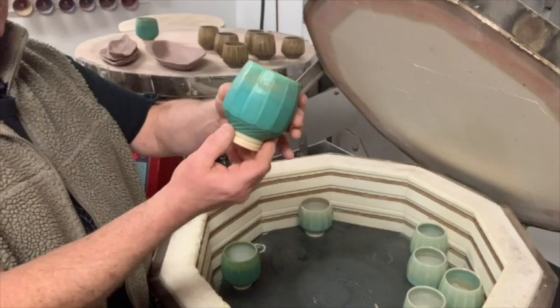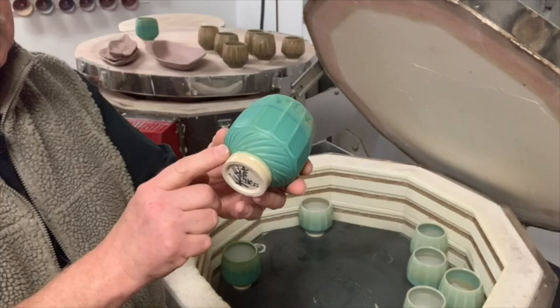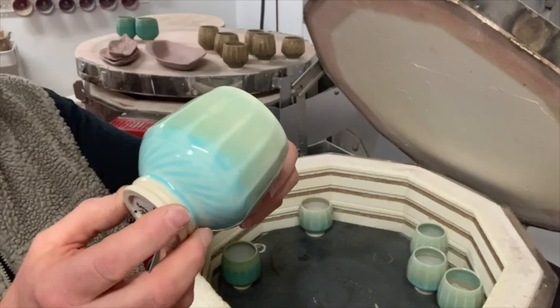Turquoise, and it's a beautiful glaze, but I think it's the B-mix. I don't think it will do this on the other cone 6 clay that I use, but it's dunting the B-mix. Same B-mix clay, but with my turquoise and my yellow oatmeal over the top, and it's not doing it to that. So it is the glaze.